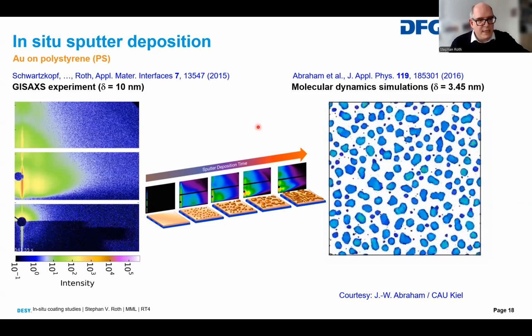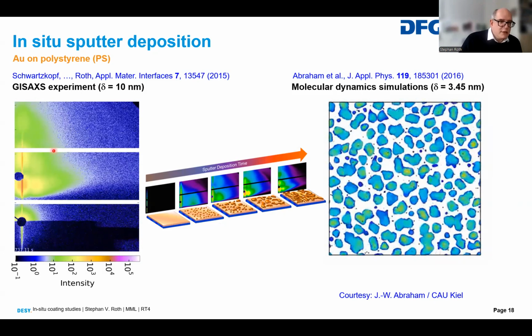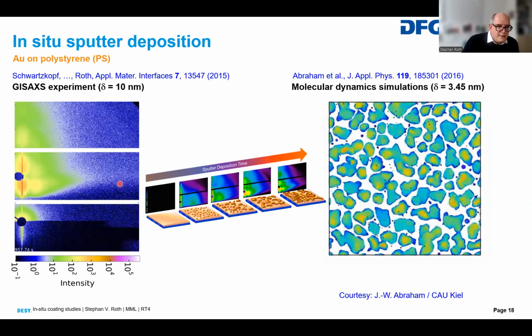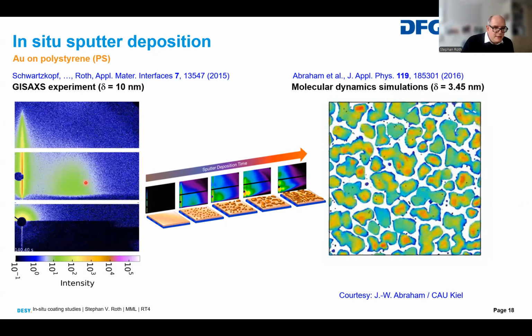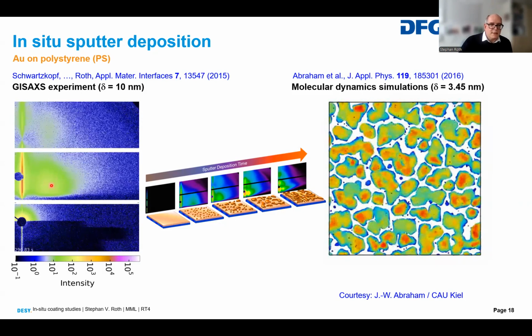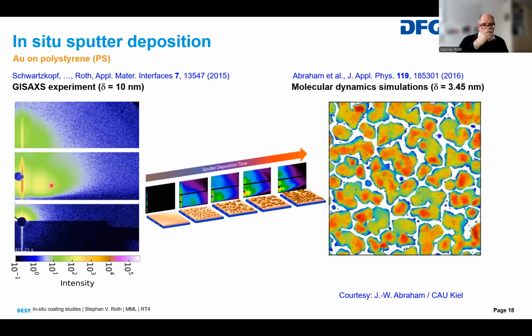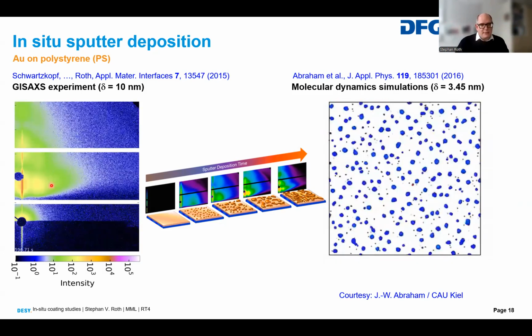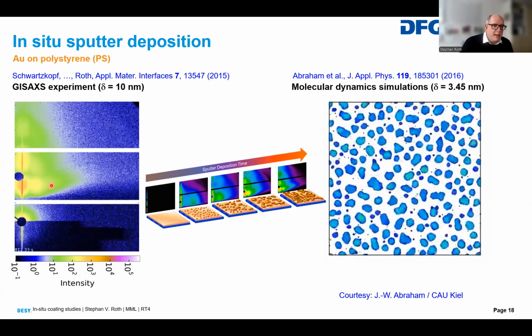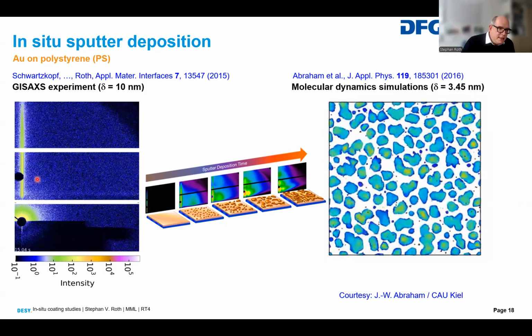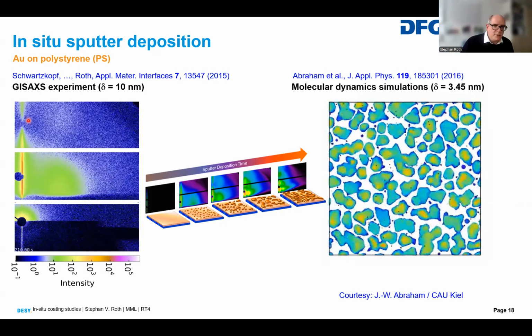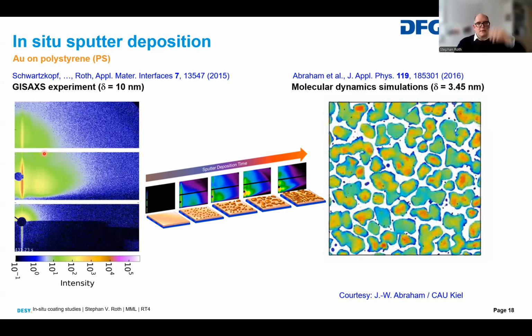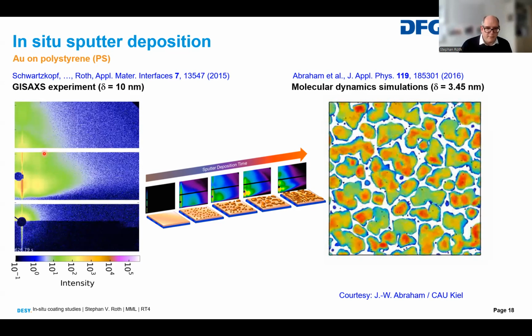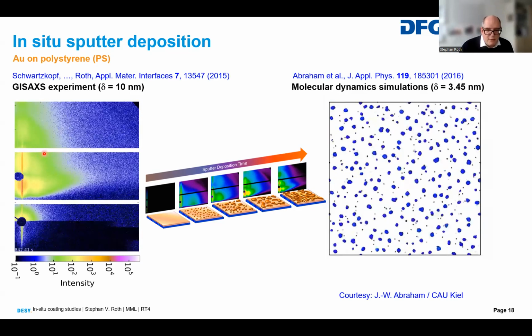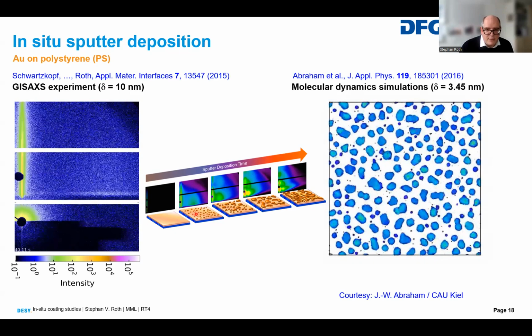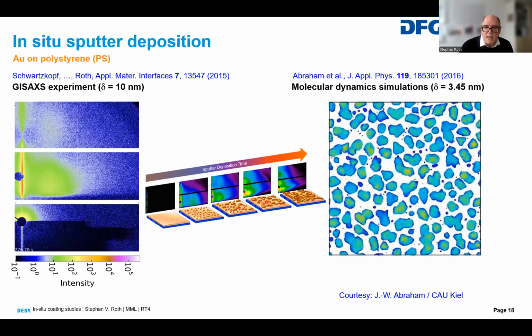You see here the evolution of the nanostructure. If you look closely, let's wait a second time. Here you see a peak going in. So when this peak moves in, this is in reciprocal space, of course, this means that the nanostructures are growing. At the same time, you see here that maxima come from the top. This means that the nanostructures are growing in height. Perfect. So we can deduce our growth, in that case, of gold clusters on a polystyrene film up to the percolated regime.